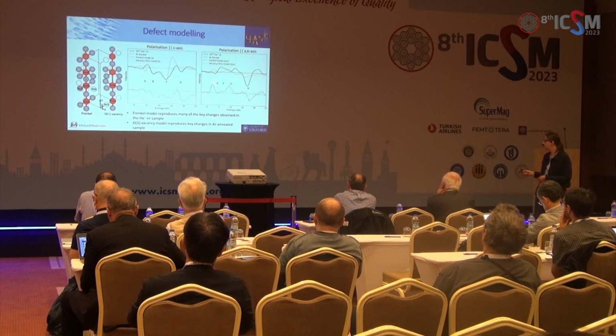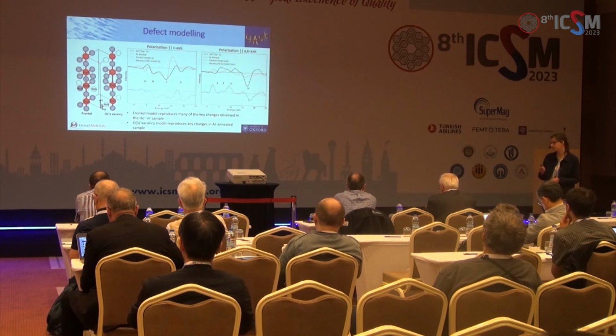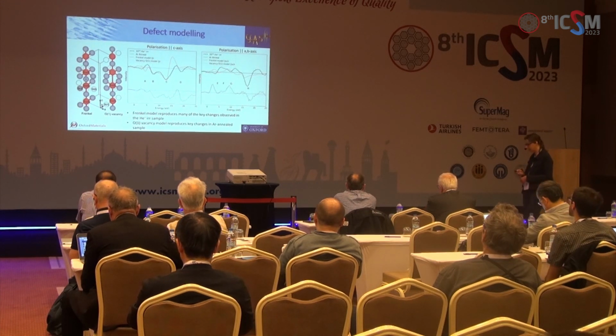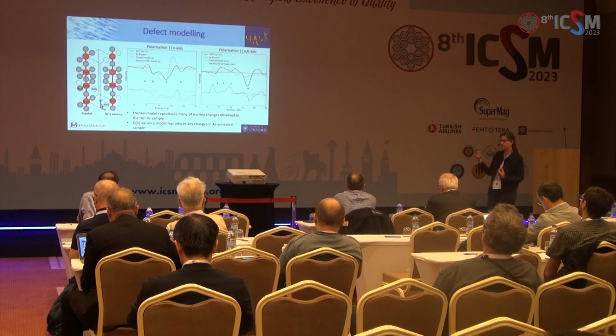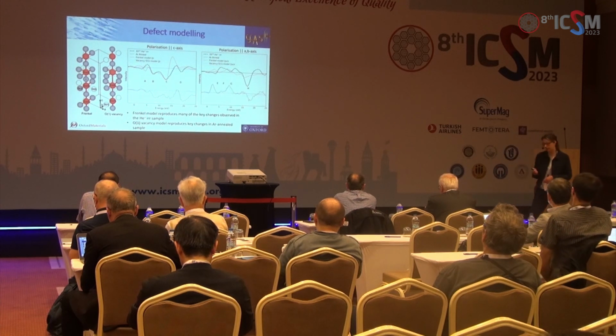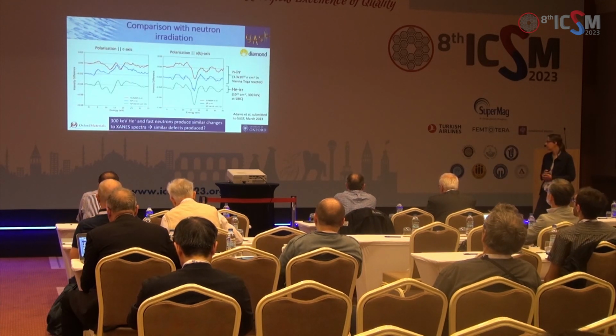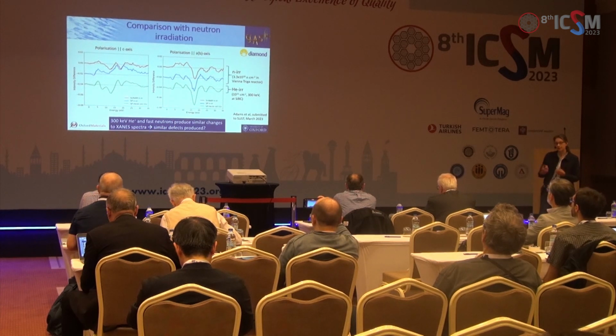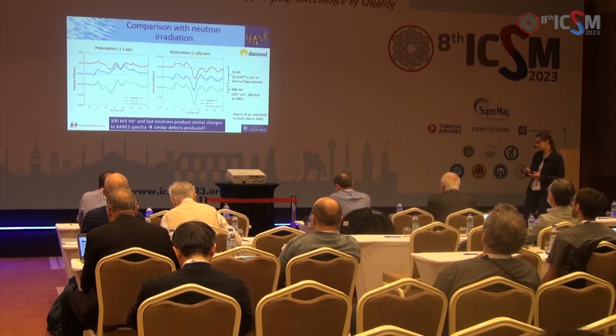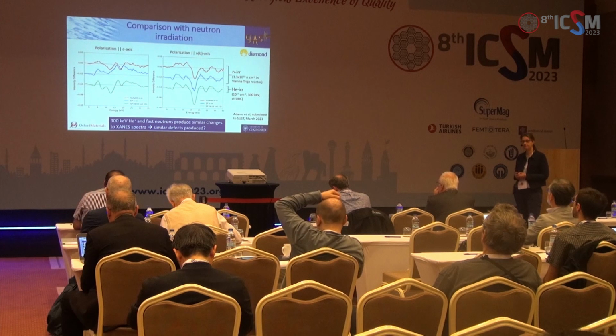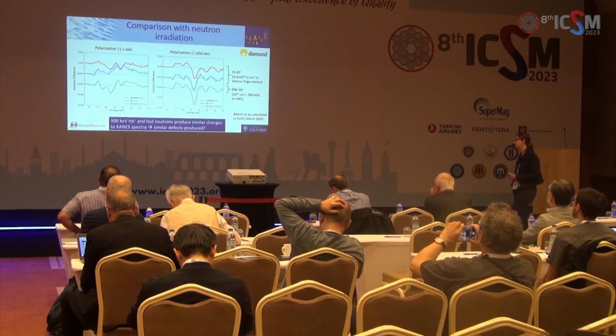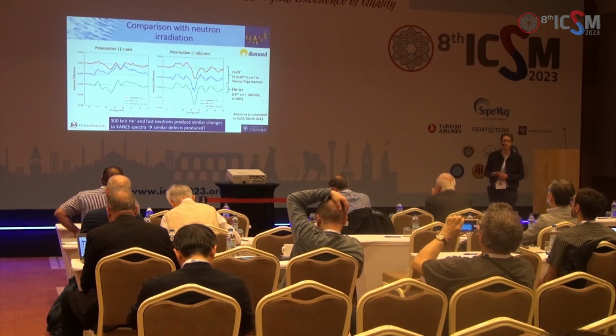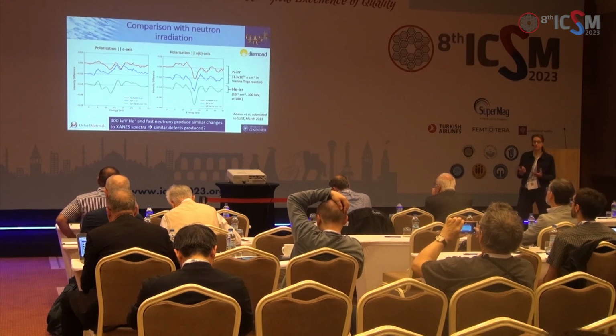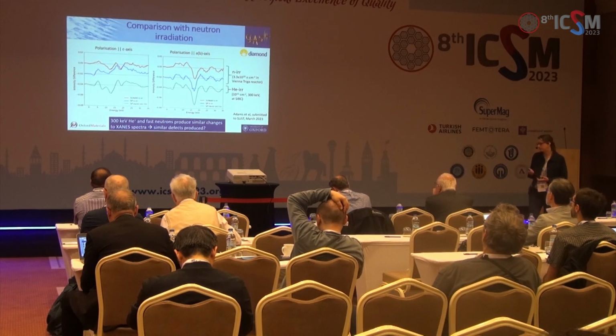This peak here, incidentally, is caused by copper in the 1+ oxidation state, which you get when you pull out that oxygen. And we definitely don't have it in our irradiated samples. So we're not just pulling oxygen out like we do with the argon annealing. So we've got some idea of what kind of defects might be in this sample. I wouldn't say we've found exactly what's going on, but we've got some ideas about what kind of defects there might be. So what happens with neutron irradiated samples in comparison?